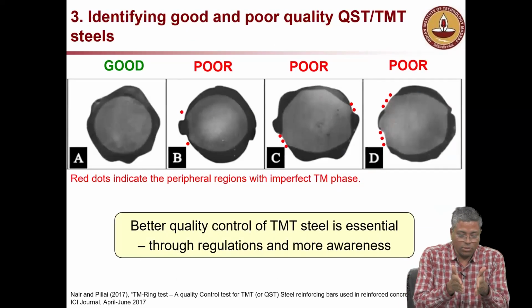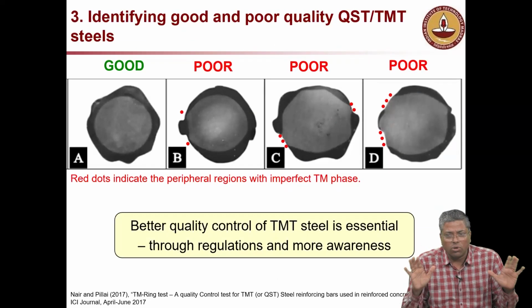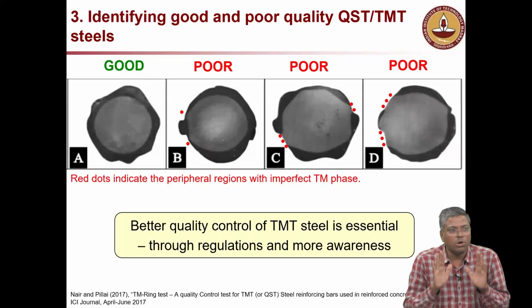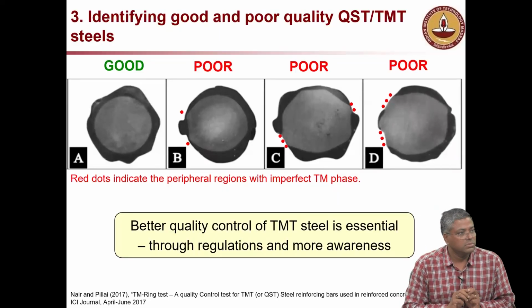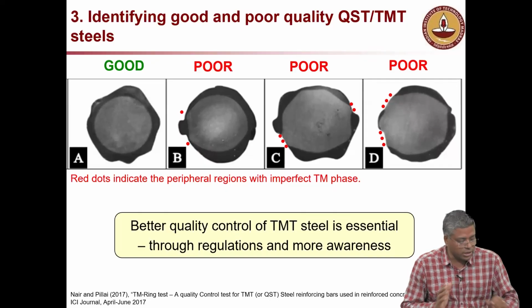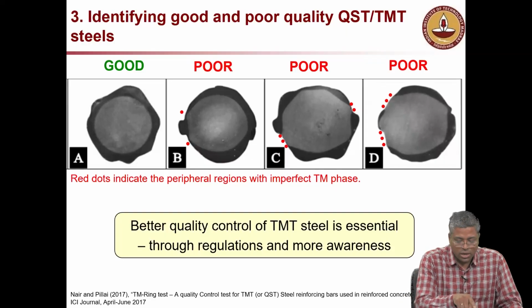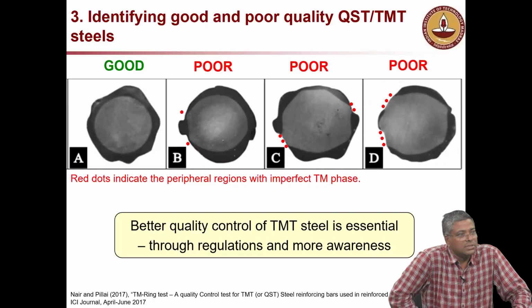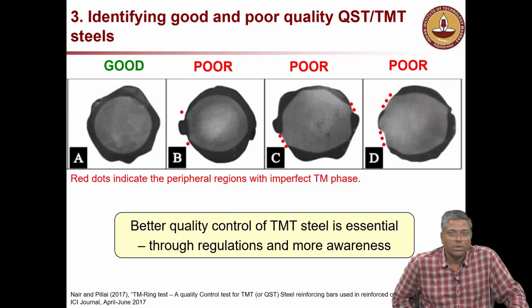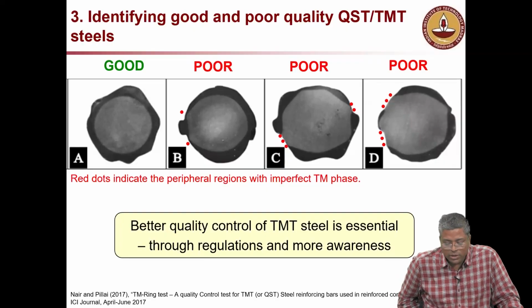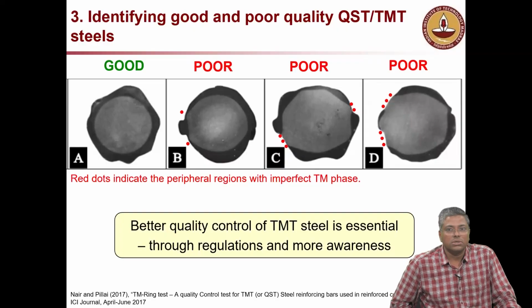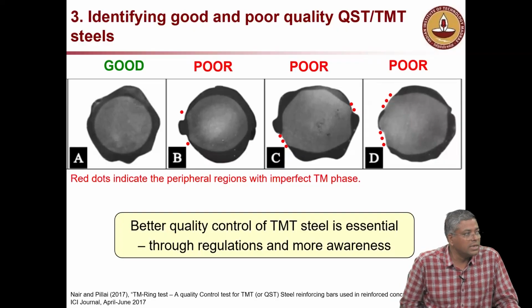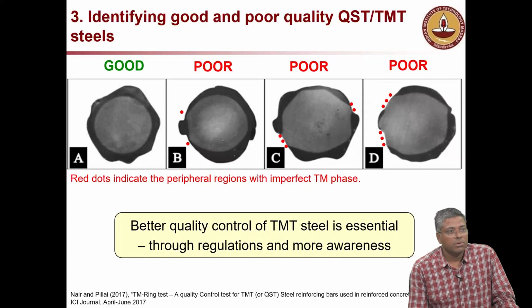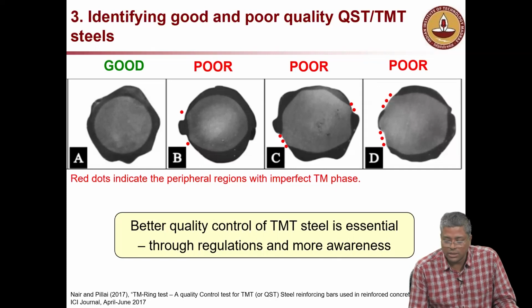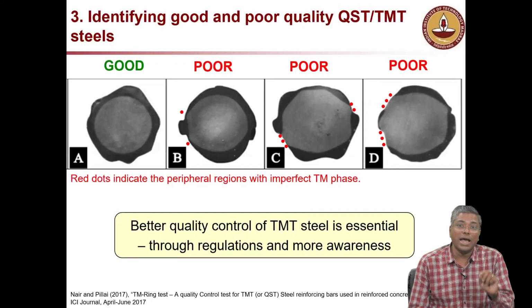We got a lot of bars, and we found the problem is only in our products. All the European products have a very good ring, whatever we test. So it is doable. It's not that it is not doable. I'll show you that also a little bit. The one on the left side is a good bar. The remaining ones with red dots show an inadequate ring, which are actually regions of poor quality, and that is where you can have galvanic corrosion.